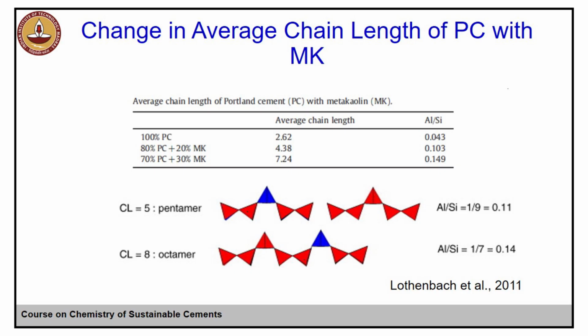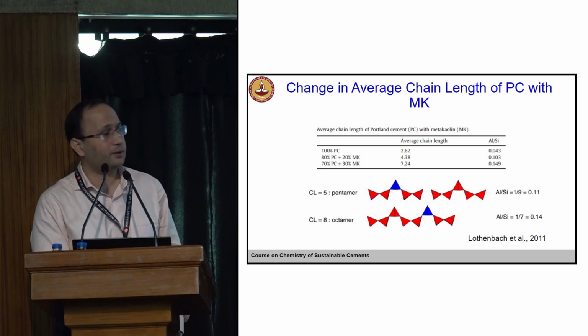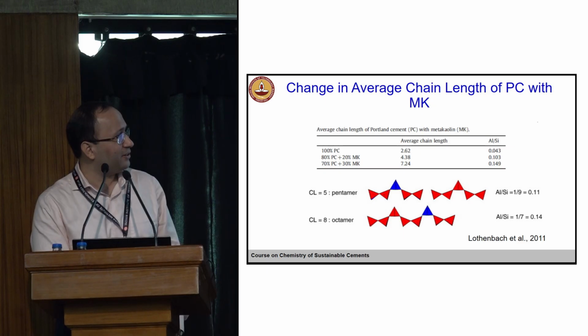Okay. So typically what we see here, this is 100% Portland cement. And as we add metakaolin, that's just an example, a reactive aluminosilicate material, your chain length is increasing, right? It goes up from 2.62 to 7.24. And you see here again this chain length. This one is an example where you have a chain length of 5. This is a pentamer, right? So 1, 2, 3, 4, 5. Here you have an octamer.